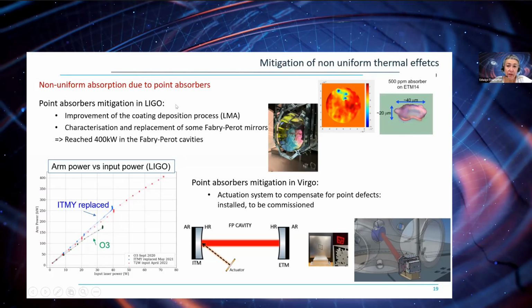And in LIGO, it has been decided to characterize and replace some of the Fabry-Perot mirrors which had most of the point defects. And it was quite a success, because with the new coating process, this problem has been reduced. You can see here the power stored in the arm as a function of the input power. You see that in O3, it was limited by these point absorbers. And after the replacement of, I believe, the mirrors with most point absorbers, it was possible to have a much more linear correlation between the arm power and the input power, showing that the impact of those point absorbers was well reduced.